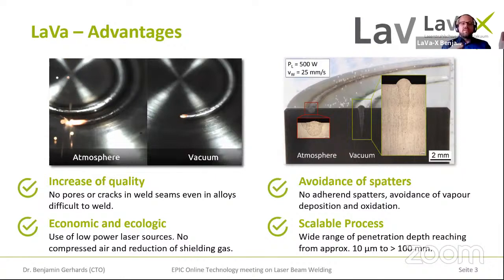So you can see on the left side at ambient pressure, we have a plasma plume, a large amount of spatters, and a huge molten pool and a huge dynamic in the process itself. If you look at the right side with the same parameters, we have no spatters, no plasma plume, and a significantly reduced molten pool. And the benefit of this is displayed in the right cross-section.